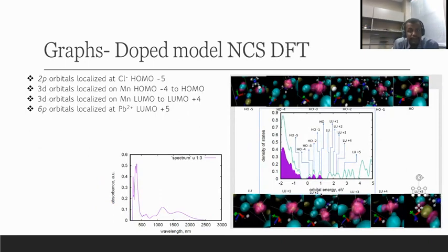So for the non-collinear spin DFT of the same doped model, we don't have alpha or beta orbital spins like I mentioned earlier. We're only going to have just orbitals. And here we can also look at the energies of these orbitals and identify where they are on the density of states, and also look at the orbitals and confirm where they are localized, so we would understand the transition between HOMO and LUMO, and which ion contributes to this transition.